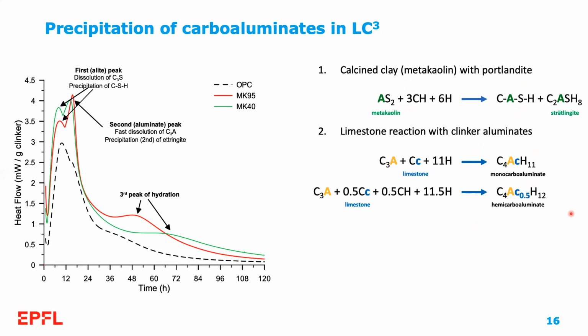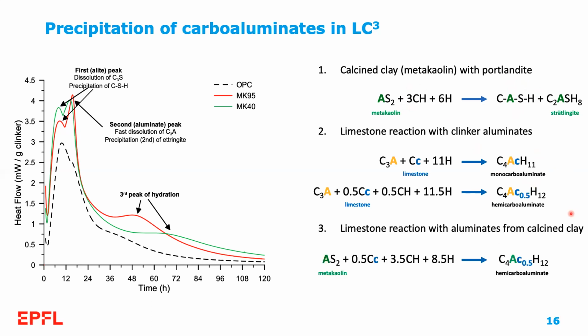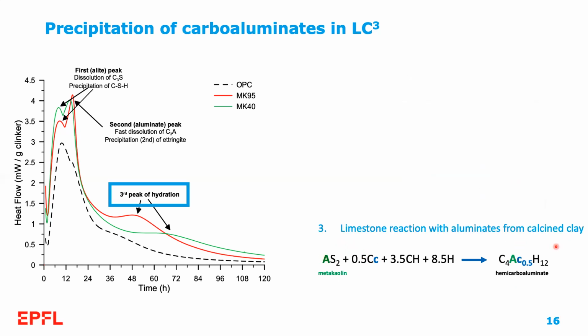And in LC3, we have a third reaction, which we call the synergetic reaction, where the aluminates from calcined clay replace the alumina from clinker, because we have another source of amorphous alumina here, very reactive, that can react with the calcium carbonate and portlandite in order to form more carboaluminates. That's what we would not observe in the case of a cement not incorporating calcined clay. By systematic exploration of these different reactions and by doing selective experiments to try to decouple these different effects, we were able to associate this third peak of hydration with this reaction here, what we call the synergetic reaction between limestone and calcined clay.